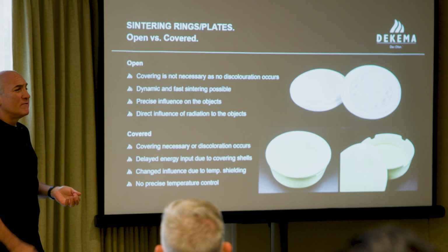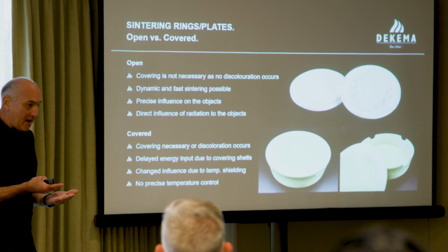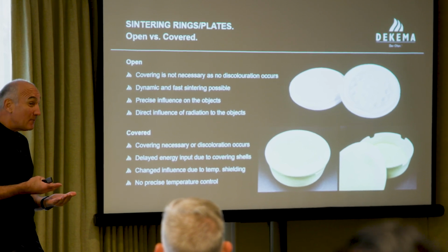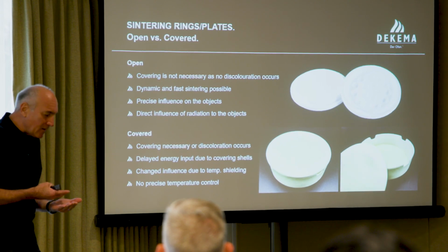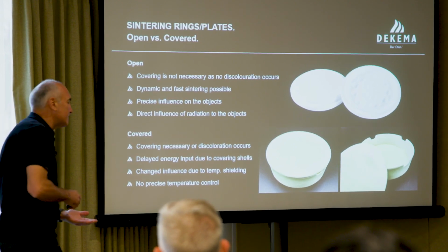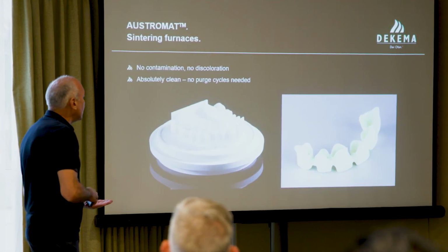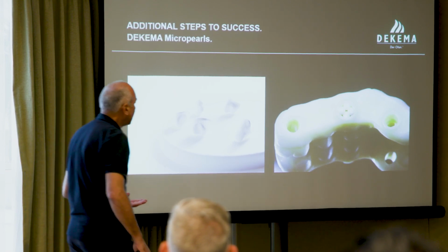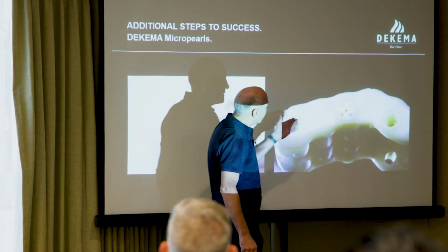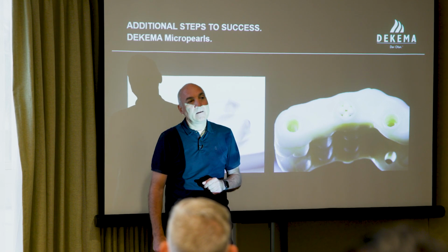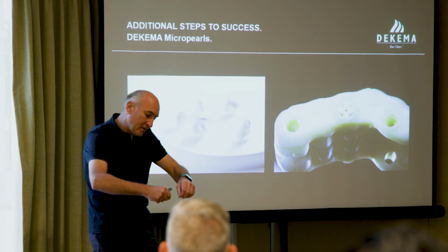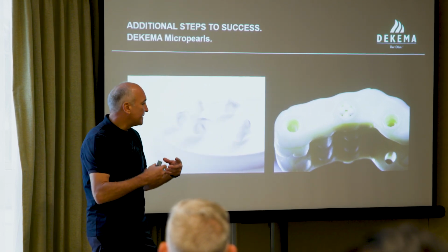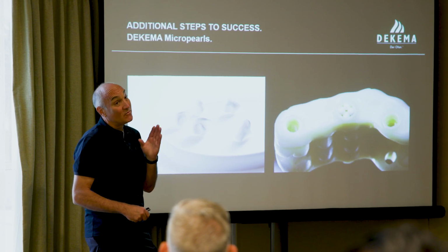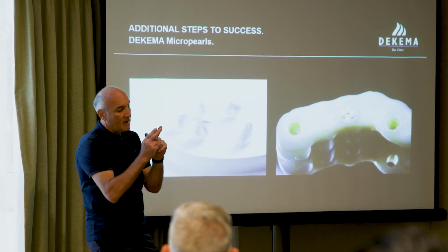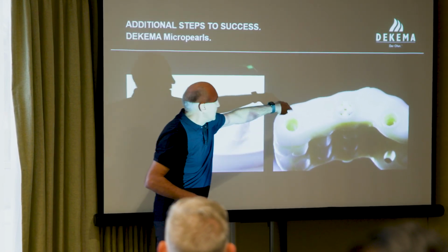But why are you working with a thick layer of pearls? To stabilize the zirconia. It's not really stabilizing. It's even worse. Now, where is it? Here it is. Because with a thick layer of micropearls, if you put it in and they shrink the zirconia, you easily get destabilization in between or even in these.